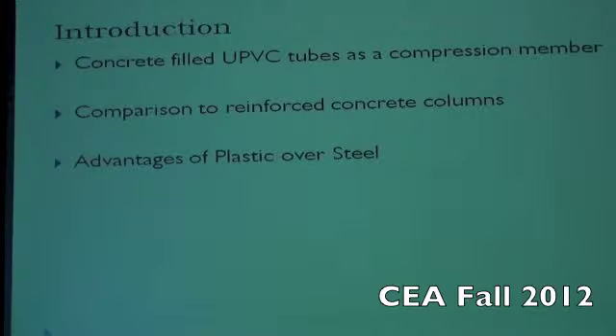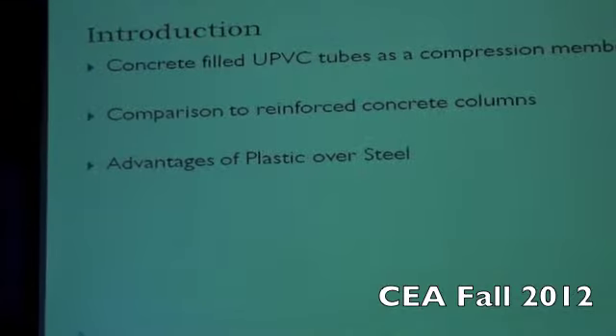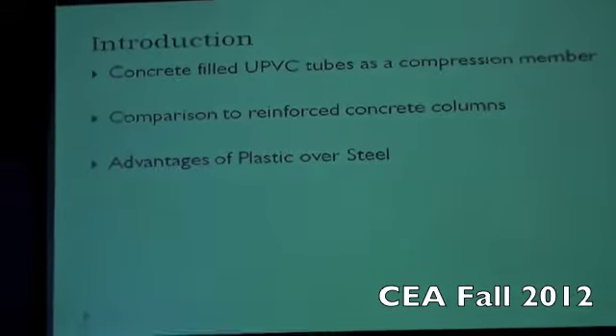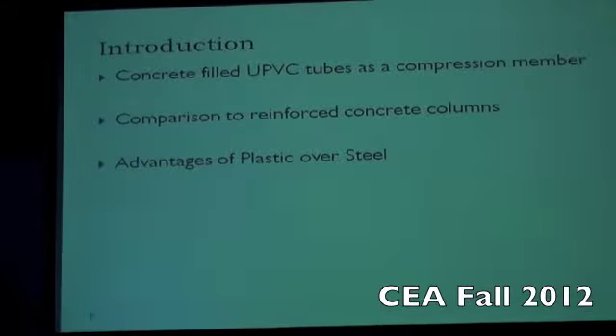We're using concrete filled UPVC tubes as a compression member. Basically, we're getting UPVC pipes, cutting them up to different lengths, and casting concrete inside them. Then we wait for 28 days until it gains its strength, and then we perform the testing. After we get our results, we're going to be comparing this to reinforced concrete